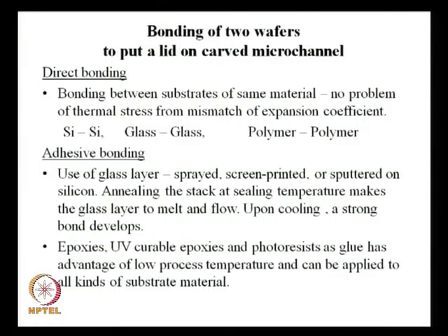Next is adhesive bonding. Adhesive bonding, here you can use a glass layer sprayed, screen printed or sputtered on silicon. Annealing the stack at sealing temperature makes the glass layer to melt and flow. Upon cooling, a strong bond develops. So, that means you have two layers, in between you put some glass. How do you do that? A thin glass layer, either you